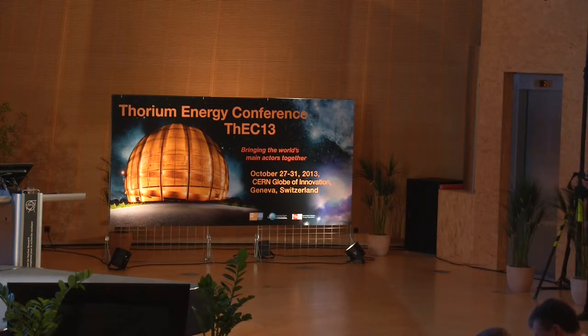So what can one do? Well, one can make some progress by thermodynamic modeling, in order to find out the thermodynamic properties. So, for example, one can construct a phase diagram for the system lithium fluoride, thorium fluoride, plutonium fluoride, and study the solubility of plutonium fluoride in lithium fluoride, thorium fluoride, by having available information on all of these binary systems: lithium fluoride, thorium fluoride; lithium fluoride, plutonium fluoride; and thorium fluoride, plutonium fluoride. Unfortunately, even this system doesn't exist. There's no data known. However, it would seem that cerium is a good analog of plutonium in this system.